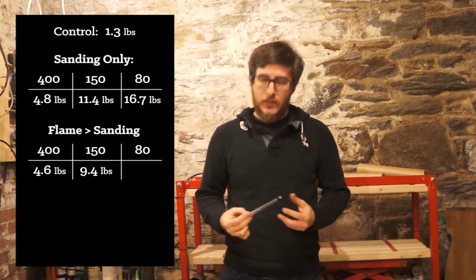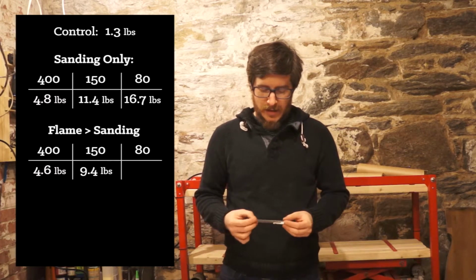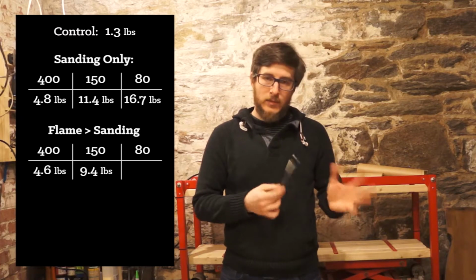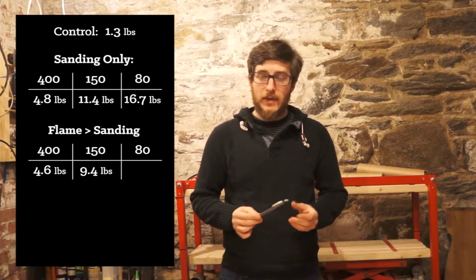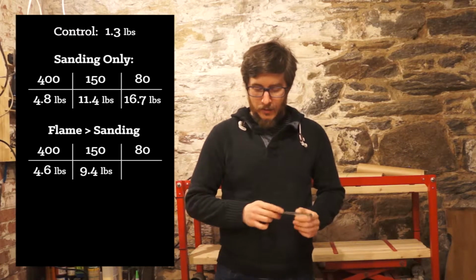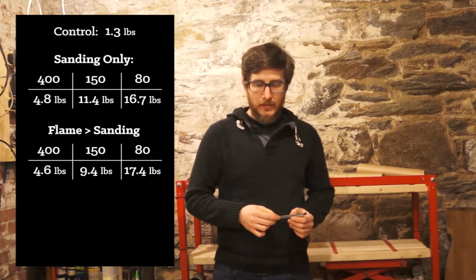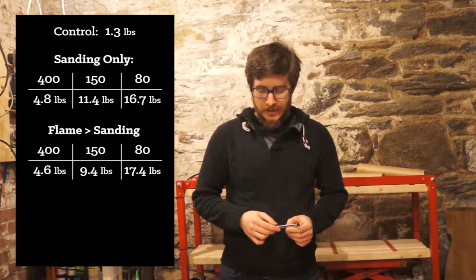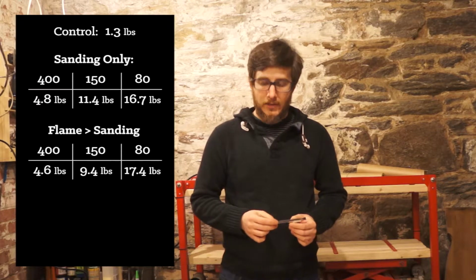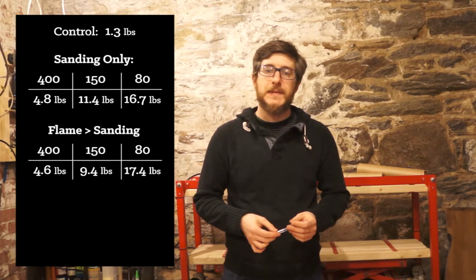And then the 80 grit was the only place that we saw an improvement with flame treating before versus just not flame treating at all. The 80 grit for that group came in at 17.4 pounds, beating out the 80 grit in the not flame treated group by fractions of a pound.